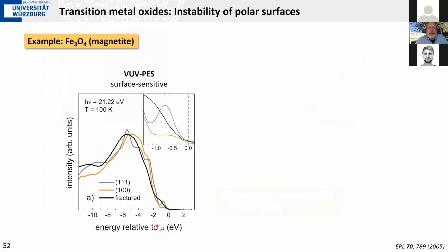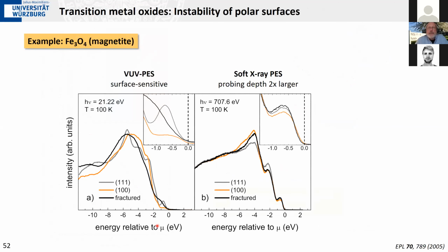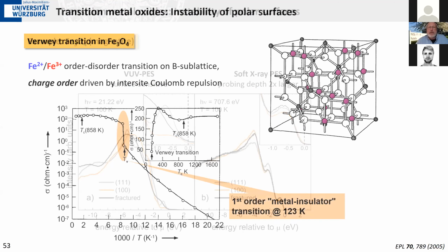Okay, let's apply this here to magnetite. This is the same surface that we just looked at with helium-1, now at 700 electron volts. It's not hard X-ray, it's still soft X-ray, but it's already much higher in probing depth. And you can see that the spectra look much more similar now, and especially close to the Fermi level, there's much more similarity than you have at these low, surface sensitive photon energies. And therefore, we have a much better probing depth.